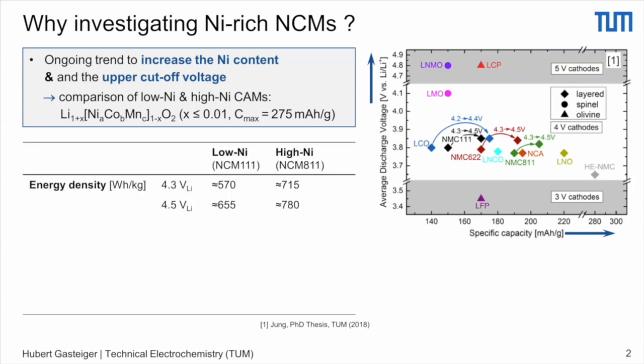So if we look at the energy density, the energy density increases with nickel content. So if we look here at the potential of 4.3 volts versus lithium, so this would be 4.2 volts in a full cell, you go from NCM 111 to 811. It's a significant increase in capacity. And the same is true, of course, at 4.5 volts, where you can get significant gains.